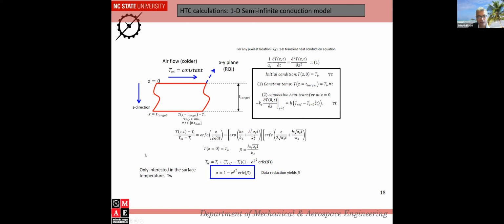And then we convert this equation, which is the equation in a very standard undergraduate textbook, and then say put Z equal to 0 here, which is the T wall temperature. And then we put Z equal to 0, this term vanishes, this term becomes 1, this term vanishes, and all we have is this beta term, which has the heat transfer coefficient in it. Alpha is the thermal diffusivity of the plexiglass, and K is the thermal conductivity of the plexiglass, and T is the time at which the T wall appears. So you know T wall and time. The only unknown here is the heat transfer coefficient. We know the properties of the material because it's plexiglass.